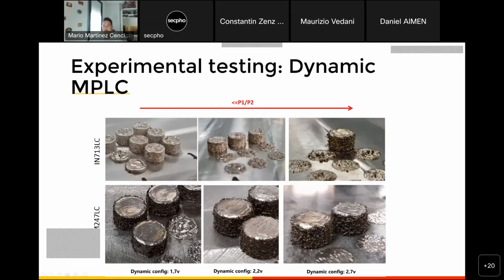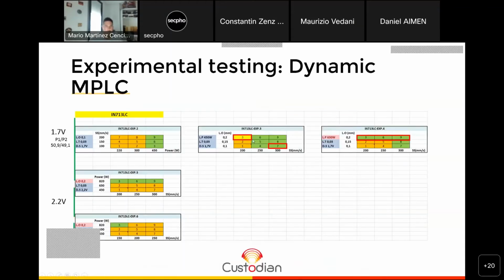Last minute, Mario. We can clearly see that when increasing the energy of the secondary beam, the surface roughness is heavier because it is creating this balling issue in the contours. This phenomenon is clearly observed in these images when varying the voltage of the galvo mirrors. All in all, I will try to speed up my speech.